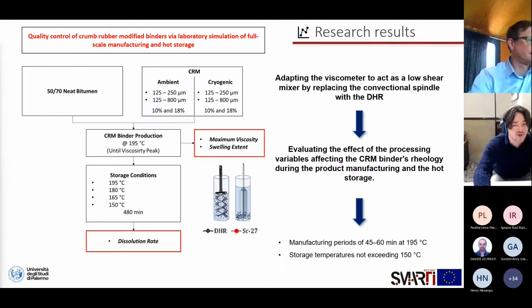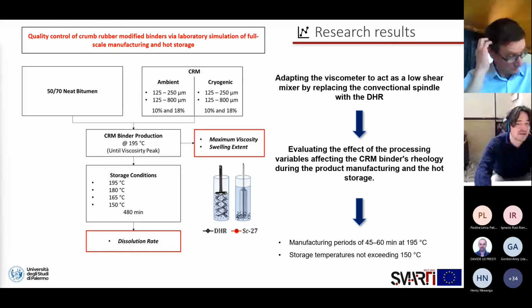Finally, in a further investigation, the adoption of the dual helical ribbon is proposed for real-time monitoring of crumb rubber modified binders during manufacturing and hot storage. The aim of this research was to evaluate several crumb rubber binders with different crumb rubber modification types and contents. Binders have been manufactured and tested at different storage temperatures to show the capability of this procedure.